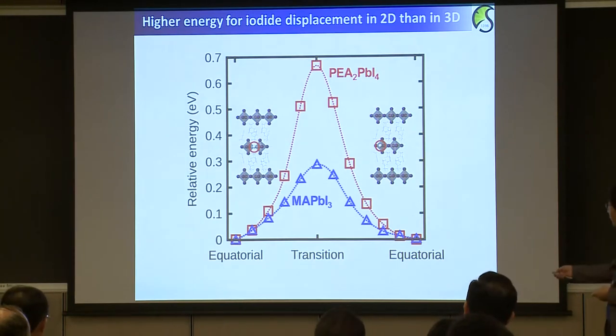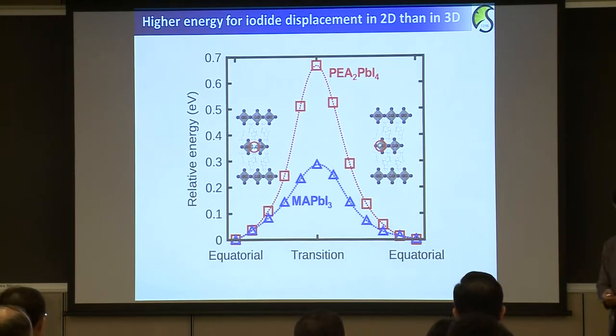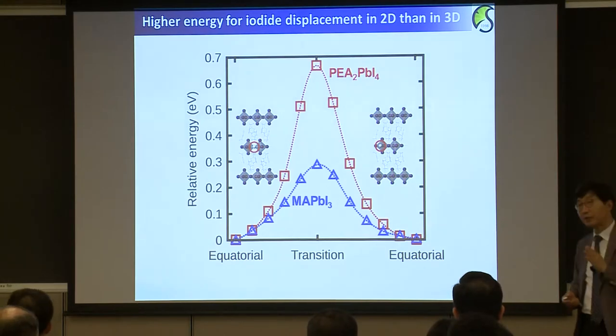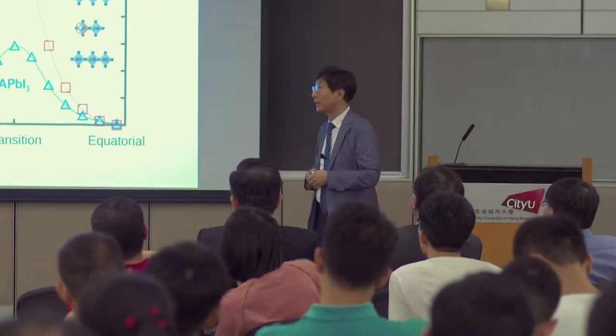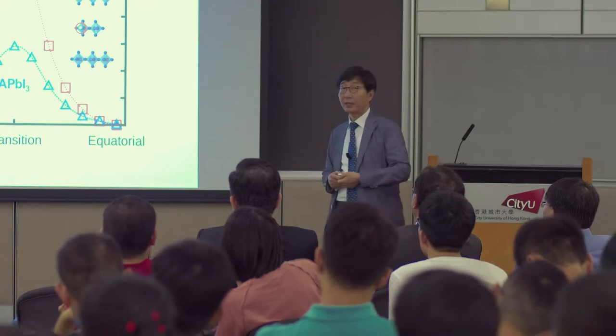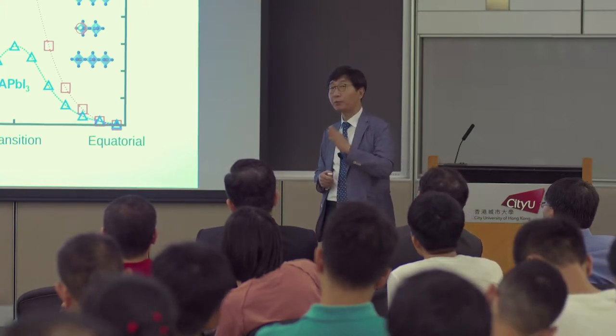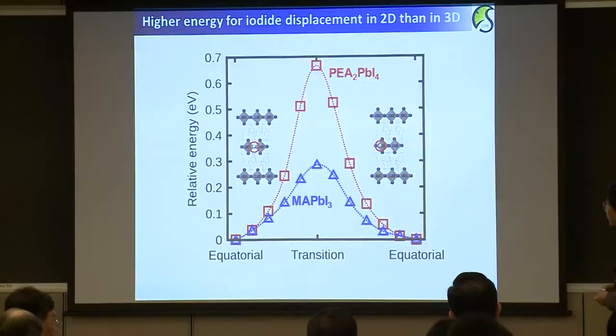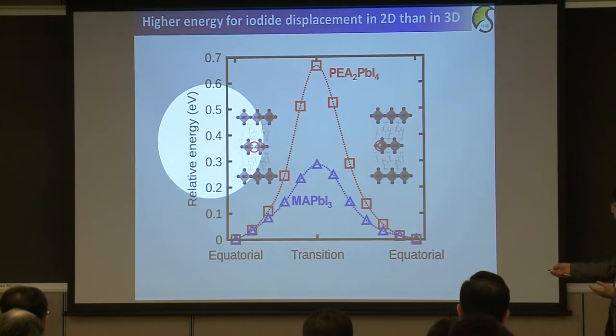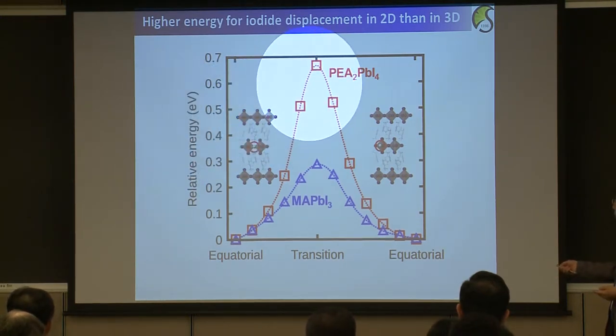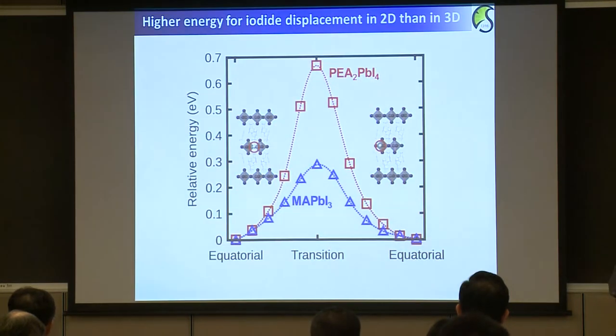So for instance, insertion of two-dimensional perovskite reduced the IV hysteresis. Probably the ion migration is suppressed by this two-dimensional structure. So the calculation results show that the barrier energy for the iodide migration is higher for the two-dimensional structure than the three-dimensional structure. So probably this suppresses IV hysteresis.